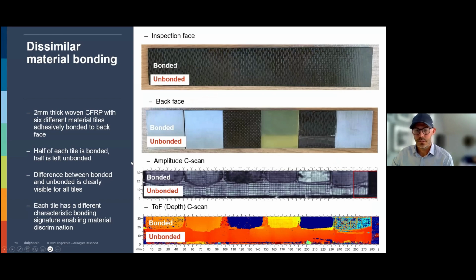One of the last ones I'll show you is a bonding structure. So carbon fiber bonded to carbon fiber or carbon fiber bonded to anything else is also very easy to detect here. And depending on the speed of sound and the other material, you can also measure the thickness of the part behind the transducer, but you can measure this both from the carbon fiber part or from the metal part. And you can see on the amplitude C-scan and the C-scan time of flight how this is detected.